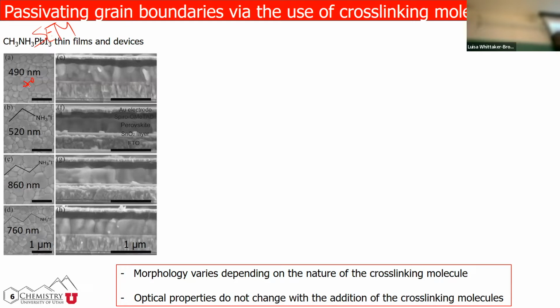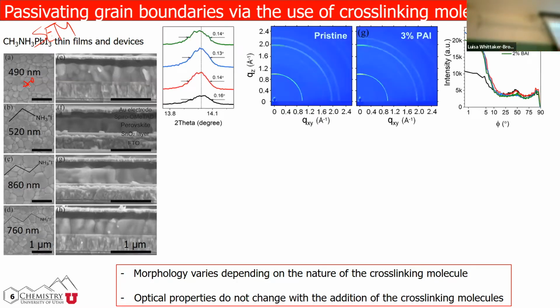Okay, so then we said, well, can we actually look at what is happening in terms of 2D maps to understand what is happening at the surface and the bulk of my material? So we actually did another technique that is called GIWAXS, grazing incidence wide angle X-ray scattering. So in the Qz, we are looking at information out of plane of the film. Then in the Qxy, we are looking at information in the plane of the film. All right, so then we know that this is the signal of some crystallographic plane that in this particular case is what we call the 110 plane.